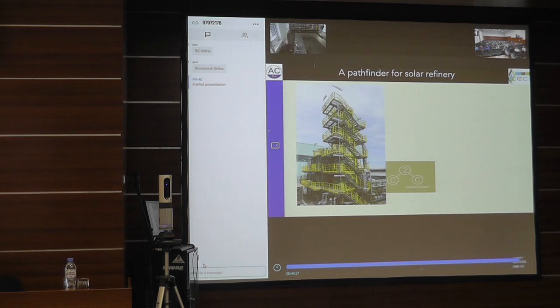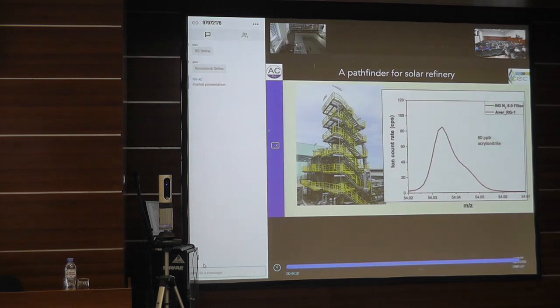And I give you just one of the challenges that we have, which is the detection of these impurity gases. You would not necessarily expect that out of a steel mill you get 80 ppb of acrylonitrile as a toxic gas that comes into this gas purifier, but in an hour it forms a monolayer of condensed polyacrylonitrile on a copper surface and the catalyst is simply dead. So these are the things that we have to study very extensively in order to solve this. And this is already an analytical challenge in its own right. We have more than 500 molecules that come in trace amounts of below 1 ppm out of this machine. So this is still an issue.